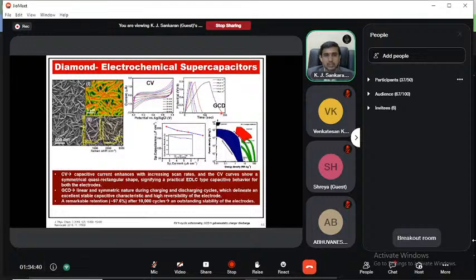As you can see here, the capacitive current increases with increasing scan rates. From the galvanostatic charge discharge studies, it's a linear and symmetric curve, showing very good charging and discharging. You can see the remarkable retention of 97.6% after 10,000 cycles, which shows the outstanding stability of these BDD electrodes.